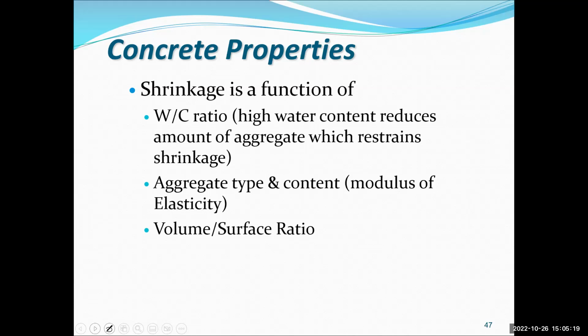It's not healthy to have a concrete that has a high percentage of shrinkage. So you want to reduce shrinkage as much as you can. To reduce the shrinkage, you need to reduce the water cement ratio. To reduce shrinkage, what you want to do is reduce water. To reduce shrinkage, you need to use aggregate with a high modulus of elasticity, which in this case has the least absorption.